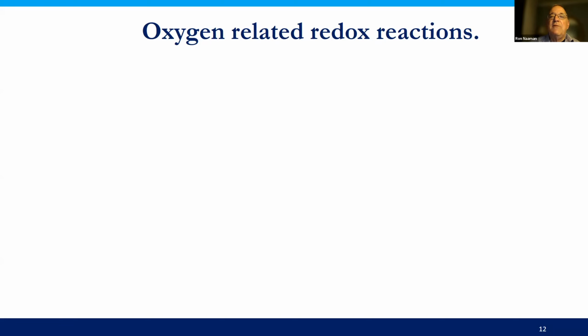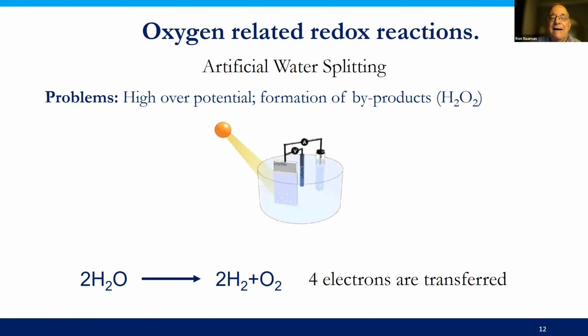But it also means that when we apply voltage on chiral molecules, the singlet of the molecule, which is an entangled state, breaks. And we know which spin is at which end of the molecule. That's a very interesting observation that relates to much of the discussion existing today about qubits in molecules and so on. So now I move to another subject, which is real chemistry, or specifically oxygen redox reactions. And the one which is very famous is the water splitting.